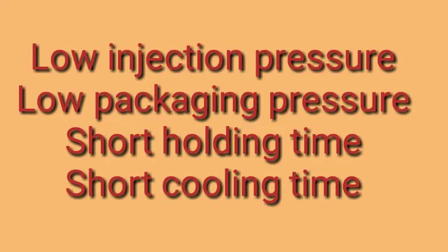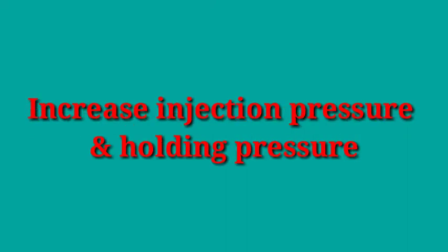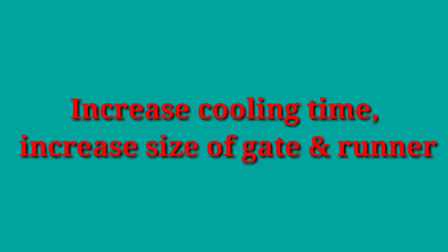Now we are going to see the remedies, how we can avoid the sink mark. We can increase the injection pressure as well as the holding pressure. Other remedies also to increase the cooling time, increase the size of the gate and the runner. These are the remedies of the sink mark.